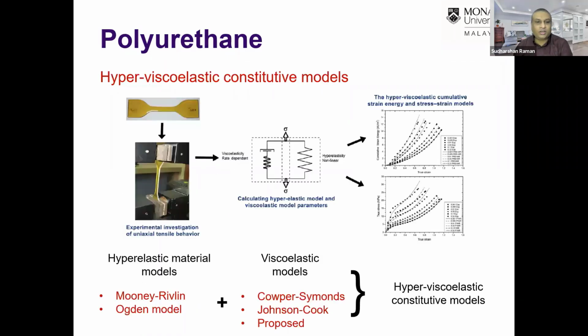Okay. And then we also tried to characterize or develop a model of the constitutive behavior of the material. What we did was we chose existing hyperelastic models, which are strain rate independent, Mooney-Rivlin as well as the Ogden model. And then we incorporated strain rate effects by using viscoelastic models of Cowper-Symonds, Johnson-Cook, as well as our own proposed viscoelastic model to account for the varying strain rate.